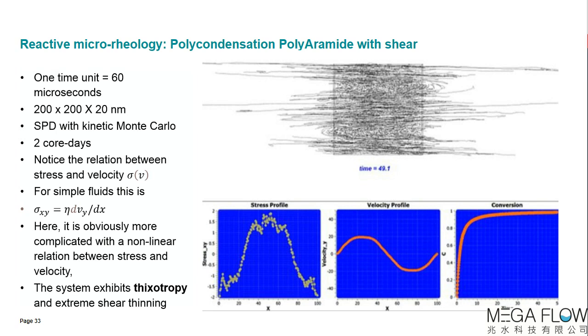The calculation you are going to see takes 2 core days, so that's still on the level of screening. If you have enough cores available, you can try many different recipes. Maybe not core minutes, but core days, I think for such a complex problem is already very fine. And then the fun thing starts when we realize that because we can measure stress and velocity, we can actually calculate the constitutive equation from a single simulation.